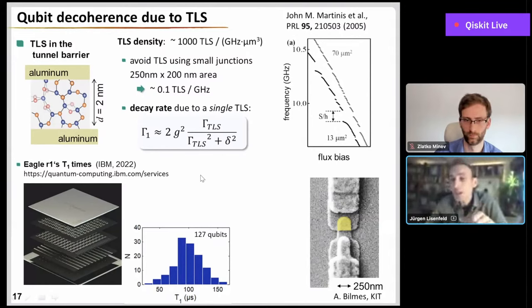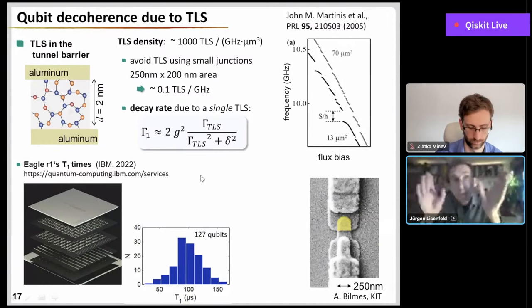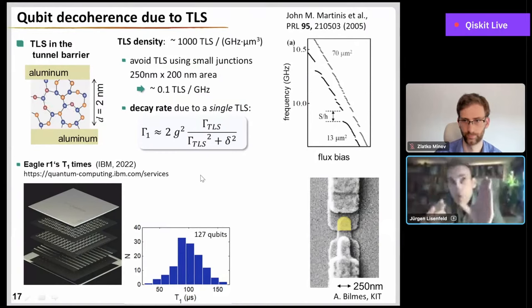So you will see that actually a glass cools down very slowly because you can also have TLS which have a very long lifetime, which is actually the tunneling time from this metastable upper state to the ground state. And that's why there can be very long living states in these glasses. But so far what we see with qubits, 100 microseconds T1 time for these defects is actually a very typical number that I find very often.